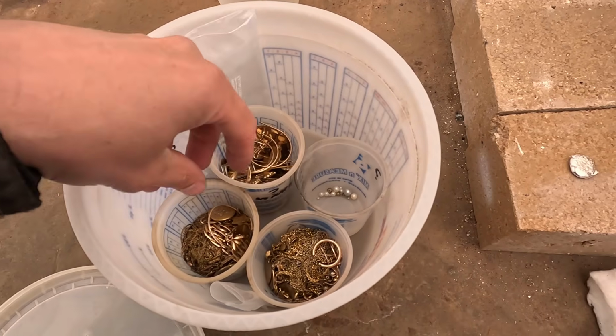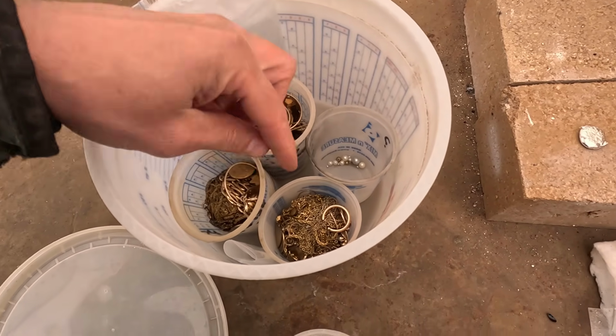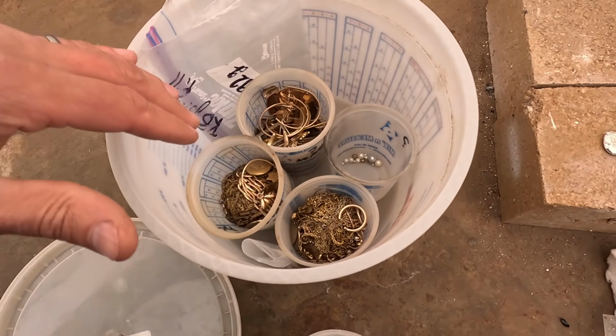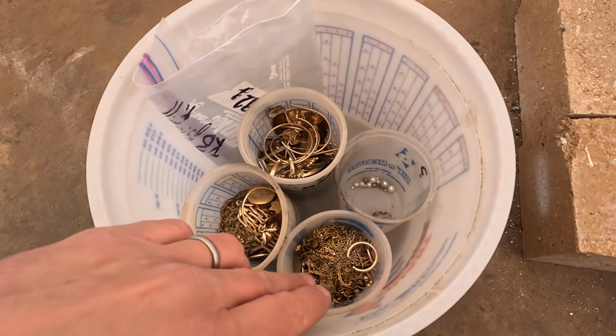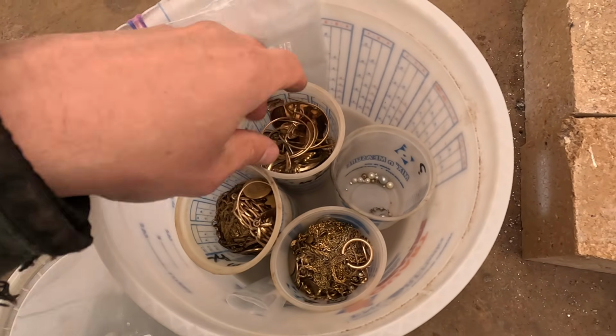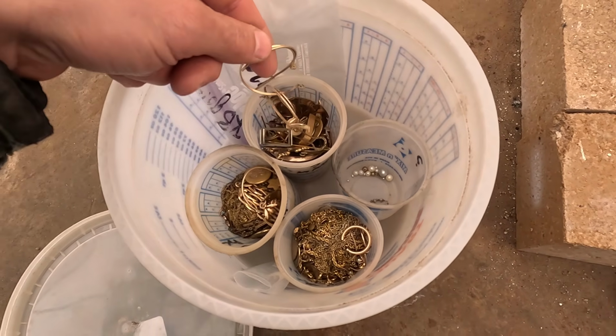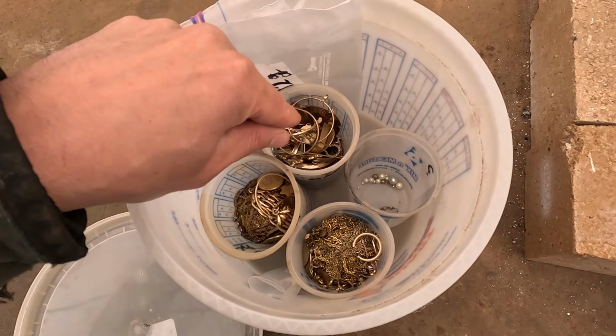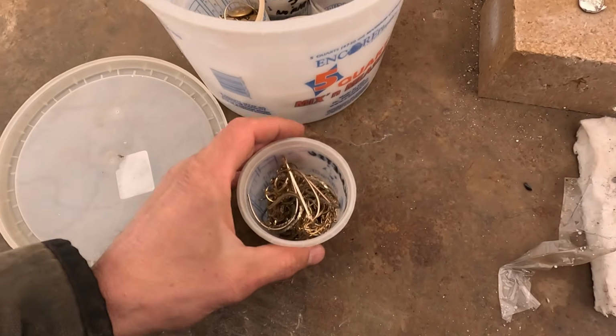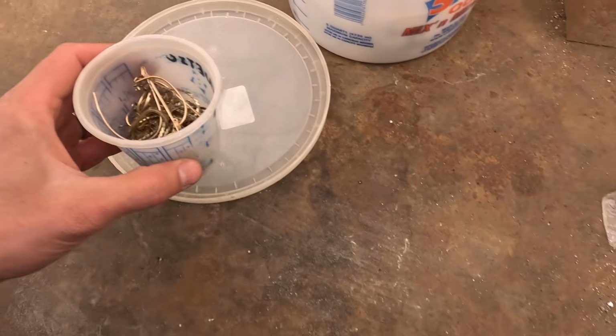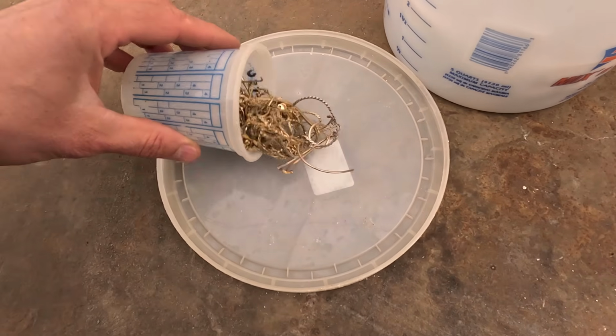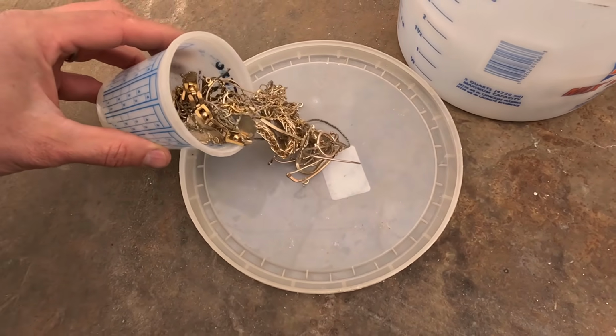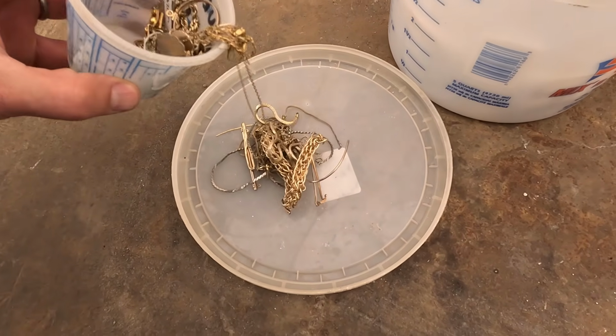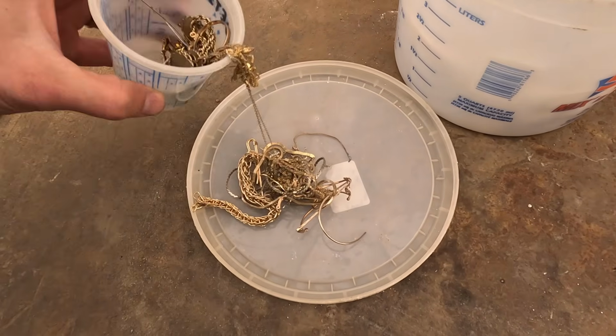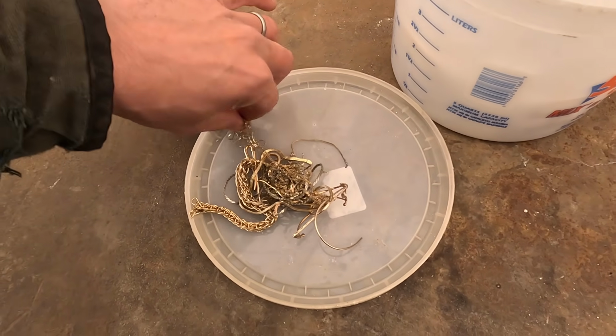Here's some of the stuff we got. Harry worked through all this, clipped all the magnetics out, and kind of sorted it into the different karat gold. We got some higher karat gold here, and this is more of the junk and the stuff that probably has some stainless steel and will be harder to recover. But what he also did was picked out all the magnetics. And the magnetics in gold-filled jewelry are typically a lot lower grade. They're more gold-plated than gold-filled.